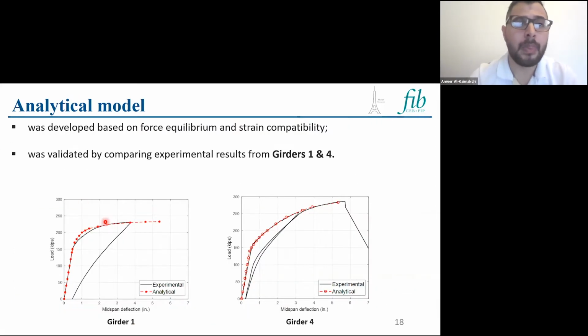We developed an analytical model to validate the experimental results. The model was developed based on force equilibrium and strain compatibility. And then we can see that our analytical results were in good agreement with the experimental results. This is for girder 1, the control girder, and this is for girder 4.